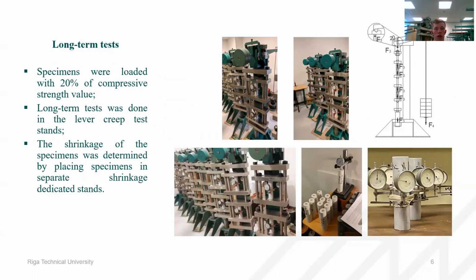Long-term tests, the creep tests took place into the creep lever test stands. Simultaneously to the creep test, shrinkage test was done, so that from the values of the specimens that were subjected to the load, or creep specimens, the shrinkage can be taken off, so to get a clean creep values. The shrinkage specimens were placed in the same environment, the same room, at the same time. The measurements were taken as the creep tests, and I'm actually at the same lab where the tests were carried out. As you can see, some of the test stands are behind me.